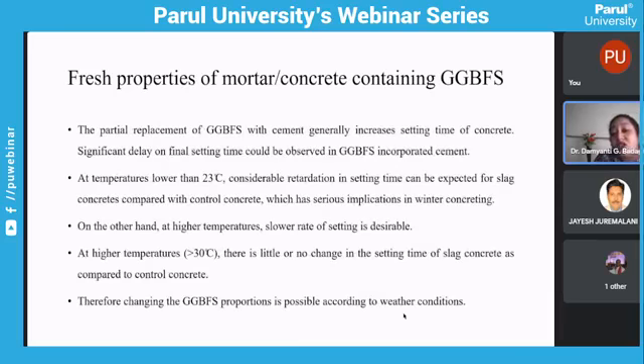And if I do not read each and every line and summarize GGBFS as per my knowledge, experience, and work, then yes, with 50% replacement of cement by GGBFS for concrete manufacturing, we can make a very good grade of concrete, like high performance concrete and high strength concrete, having good tensile properties, good flexural properties, and all the mix property parameters will be good. We can use GGBFS in a very good manner, because this is my personal experience, because I did a lot of work in that.